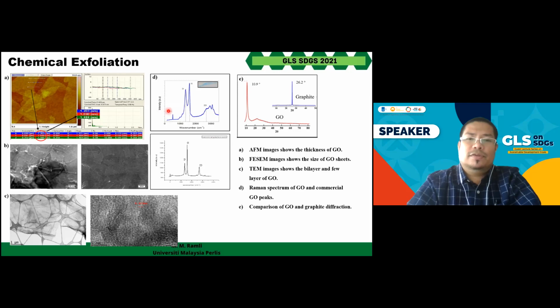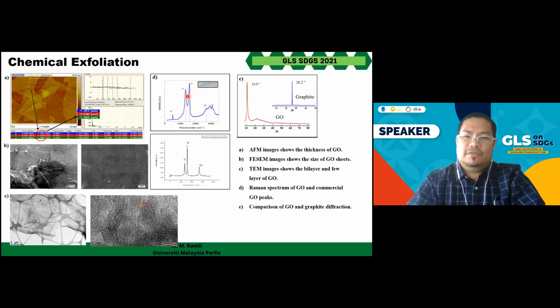And then for our graphene oxide, we did the Raman spectrum, and we compare with the commercial graphene oxide. This is a commercial graphene oxide. And this is the graphene oxide that we produce from synthetic graphite from oil palm trunk. And then finally, we did the comparison between the graphite before exfoliation and after exfoliation. This is commercial graphite, and this is the graphene oxide that we get from our synthetic graphite. Okay.